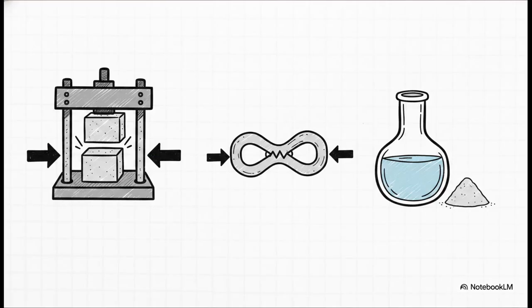Finally, we wrap up the lab tests by measuring raw physical strength. For the compressive test, we literally crush 70.6mm cubes made of a 1:3 cement to sand ratio. We use incredibly specific math for the water here, and we expect them to reach a massive 33 newtons per square millimeter in 28 days. The tensile test literally snaps briquette molds to quickly identify any quality defects. And we even test specific gravity using a Le Chatelier flask filled with kerosene, because obviously using water would instantly cause a chemical reaction. This helps us find a precise value of around 3.15. Honestly, it's just an intense physical gauntlet.